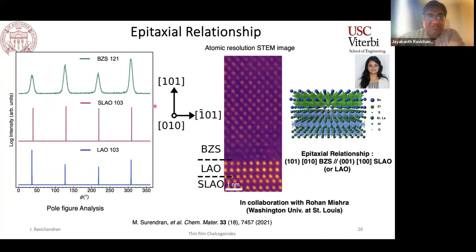We studied the epitaxial relationship in these films a little bit more carefully. If we do the pole figure mapping of these films, you can clearly see there is a one-to-one matching between the in-plane relationship of your substrate and your film. We were able to map out this relationship completely to show that you have a very unusual interfacing between the film and the substrate, where we would have nominally expected the film to rotate 45 degrees to minimize the lattice mismatch. But in these cases, it seems like you produce a large number of interface dislocations to just grow them without any rotation at all.